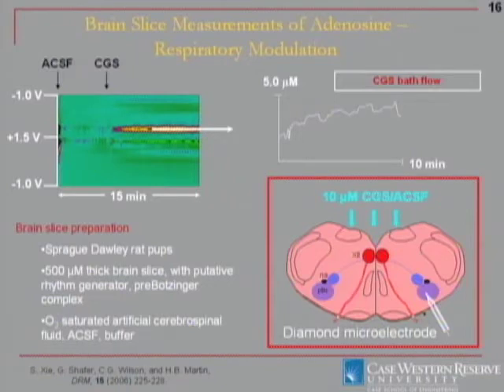So what we did here was we put a diamond electrode into a brain slice of a rat pup, and this particular experiment was to show we could see adenosine. This is important because adenosine oxidizes at a high positive potential, higher than is possible to see on other electrodes. So here for the first time we could directly measure adenosine in tissue.